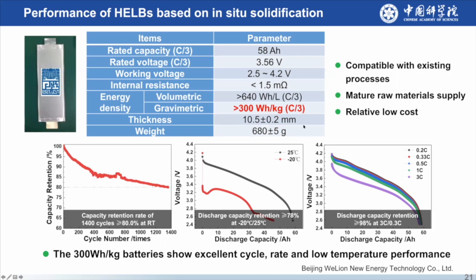With those combinations of the technology, we have tried to develop the battery with the high energy density, like in this case, 300 watt hour per kilogram for electric vehicle applications, which can have acceptable performance, like over 1,000 cycle life, 100% DOD, and also the low temperature performance and the high rate performance. Like at 3C, we still achieve 98% capacity retention.